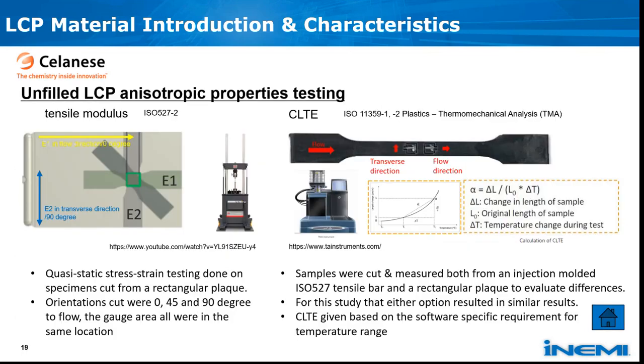Okay, very special for LCP. Polymer and resin has anisotropy already. To incorporate this into simulation, anisotropic tensor modulus and CLTE were measured based on unfilled resin. To obtain anisotropic tensor modulus, quasi-static tensile testing was finished on cut specimens with orientations. As the left picture, specimens were cut from a rectangular plaque. Orientations were 0, 45, and 90 degree to flow direction. The gauge areas were all in the same location.